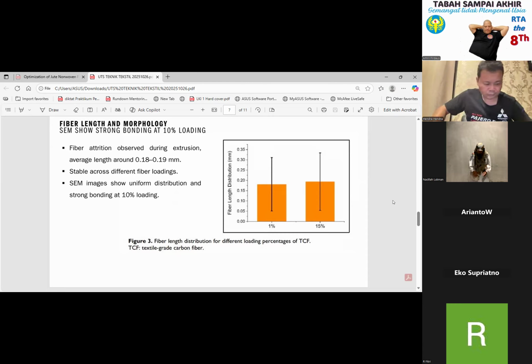Then using the SEM, or scanning electron microscopy, the research team observed the fracture surface of the composite sample. The image showed that at 10% fiber loading, the fibers were evenly distributed and well bonded with the polypropylene matrix. You can actually see the fiber breaking rather than pulling out, which means that the interfacial bonding, the glue between the fiber and polymer, was strong.